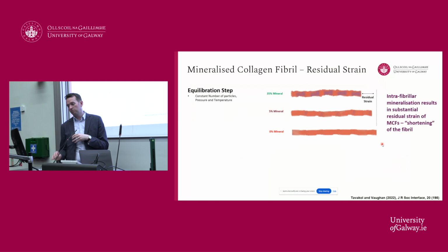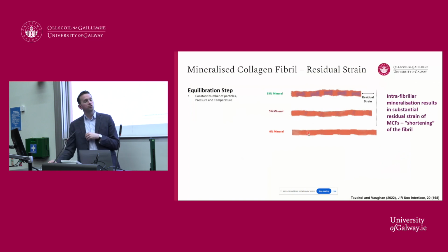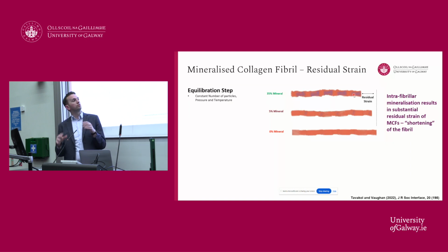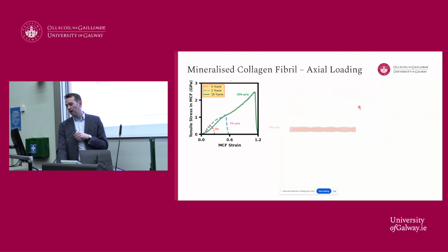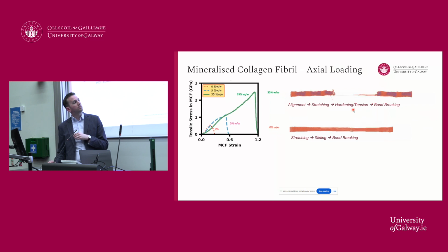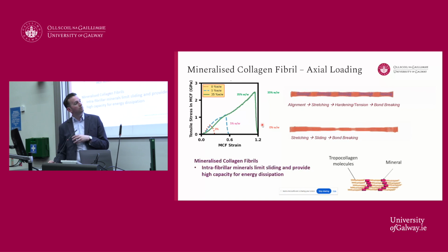And the first thing he identified is that when you introduce mineral into a collagen fibril structure, you get a shortening of this mineralized collagen structure. Okay, so you introduce a residual strain in the structure just by introducing the mineral itself. And he then looked at these simulations under axial loading. And what he found was that when you introduce mineral, you get a much stronger response from the mineralized collagen fibril. And he was one of the first to identify that the real function of these minerals in the fibril itself was not just for stiffness, but they also provide a very strong bond between collagen fibrils. And they enable a lot of energy dissipation because of that.